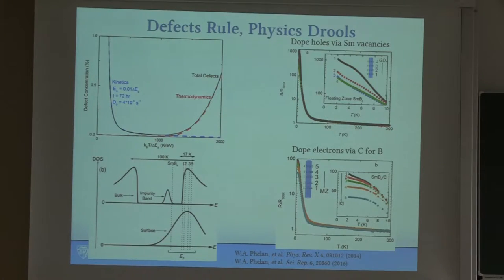But then below something about 10 Kelvin, you don't get the same number. In other words, that low temperature value is thickness dependent. And in fact, what that really means is that it's not dependent on the bulk anymore, but instead scales with some other dimension, which in this case is the surface. So if you believe that's proof of surface states in transport, then that's what you see. But the point is, the trend here is really nice. We can systematically vary that by adjusting the defect concentration in this material. We came up with this toy model that basically you have your bulk material with a bulk band gap, and then you have some surface states that are sort of weighted towards the conduction band. And as you tune across here, you can basically populate those surface states or not.